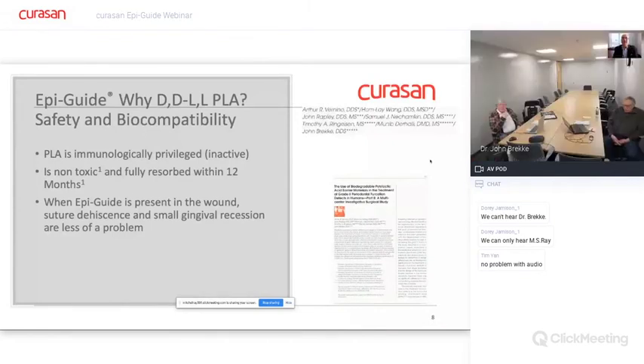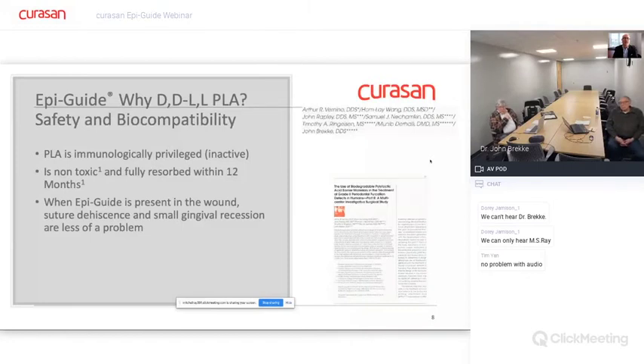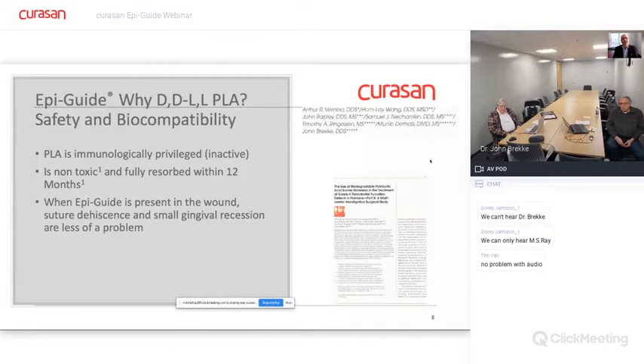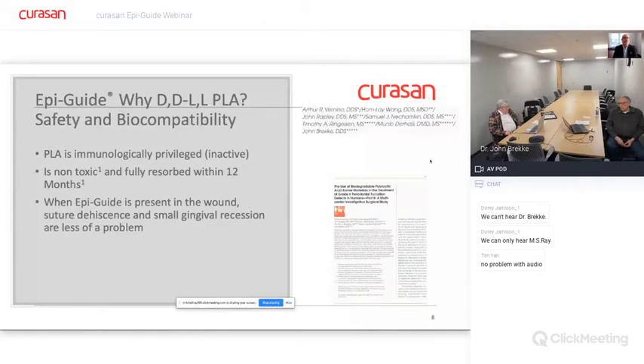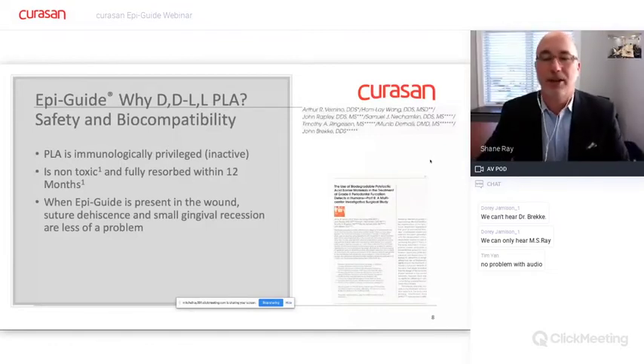There are many different species of polylactic acid, and the DDLL species is a racemic mixture of two optically active enantiomers — one bending polarized light to the right and the other to the left. The net effect of that is that DDLL polylactic acid does not crystallize, and if there are no microscopic crystallites formed as a consequence of the polymer chemistry, then the foreign body giant cell reaction is much reduced as it biodegrades away. This is described in a journal article with Dr. Vernino and Dr. Brekke describing its profile and use in periodontal defects.